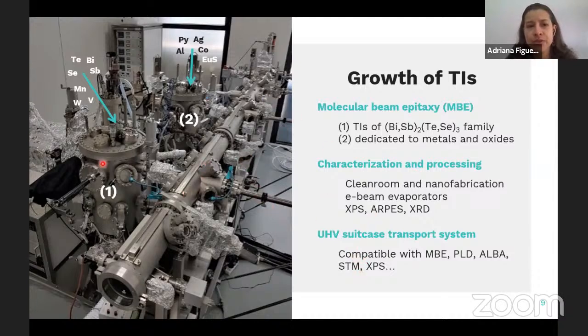And there's another feature that I want to mention here, which is relevant for the growth of heterostructures of the topological insulator thin films, is that we also count on a UHV suitcase transport system where we can take our samples that we grow in this chamber, for example our TIs, and transport them in ultra high vacuum to other chambers or other facilities, not only at ICN2, but in other labs, for example, to the Alba synchrotron or to other characterization facilities or equipment, like to do scanning tunneling microscopy or XPS, or to grow other layers like PLD, and not only to transport them from here to there, from there to here.